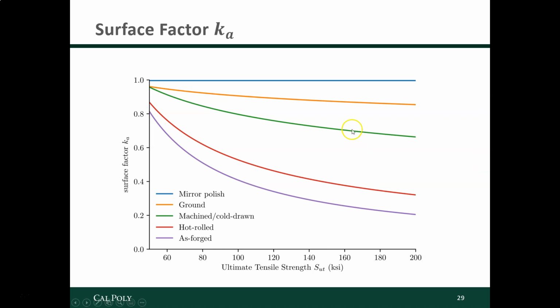So it turns out that these curves can all be approximated with a few constants. Our surface factor Ka is given by some a, this is different from that a, a constant times SUT, the ultimate tensile strength, to the bth power, where a and b are given in table 6-2 of the Shigley book. So let's do an example.